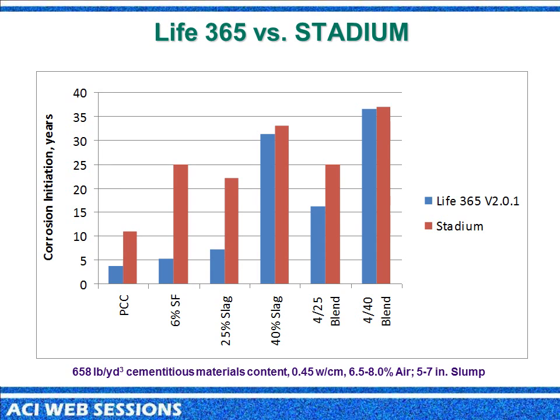When we look at the Life 365 versus the Stadium, as I should have mentioned before, these are run at 658 pounds per cubic yard at about a 0.45. Most of these were actually at about a 0.43 as some water was held back during the mixing. And these were all at 6.5 to 8% air content along with a 5 to 7 inch slump. But going back, we can certainly see that we do see differences between the Life 365 program that is available and also the Stadium program.